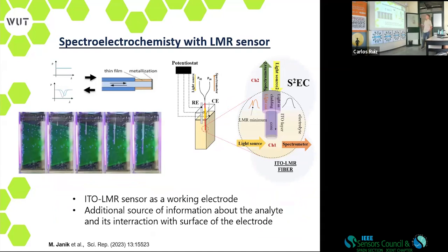So we have the standard configuration of electrodes, but instead of one of the electrodes, one of them is the fiber. So we measure this transmission here for the electrolyte and measure also the response in different places where we can locate the electrode. This time it's a metallization on the top, so it's like a probe type, so it's easier to insert it.